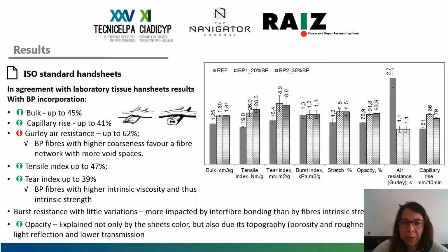As regards strength properties, we found that tensile increased alongside tear index, and these results were ascribed to the fact that we are incorporating fibers with higher intrinsic viscosity and thus higher intrinsic strength. In case of burst resistance, we found some little variations, and this was explained by the fact that this property may not be as affected by intrinsic strength variations as tear and tensile.